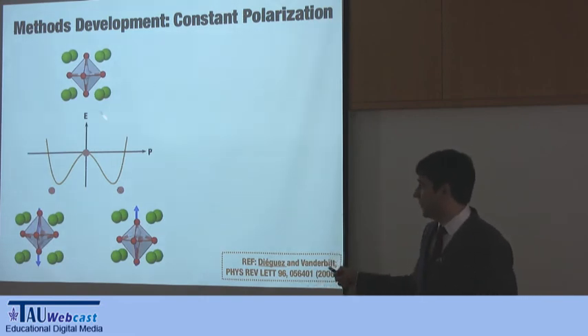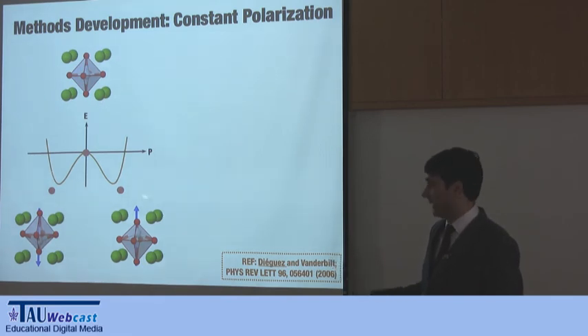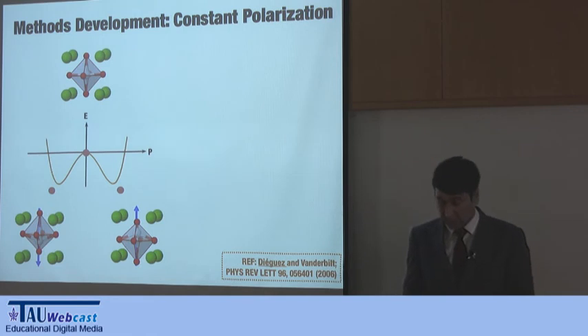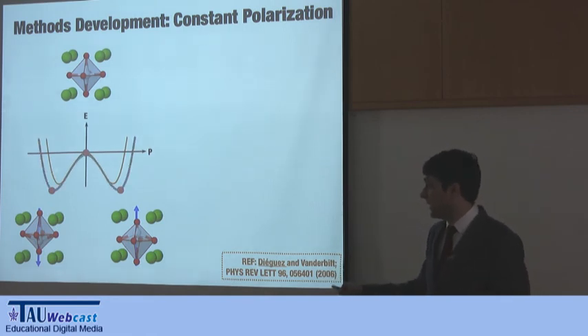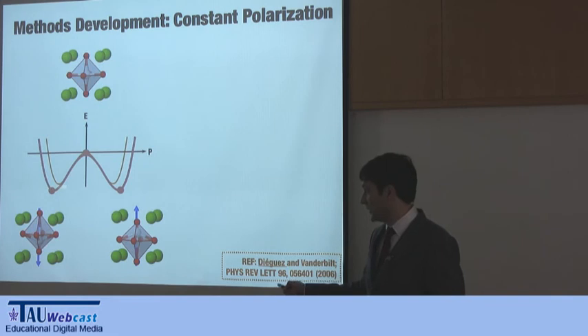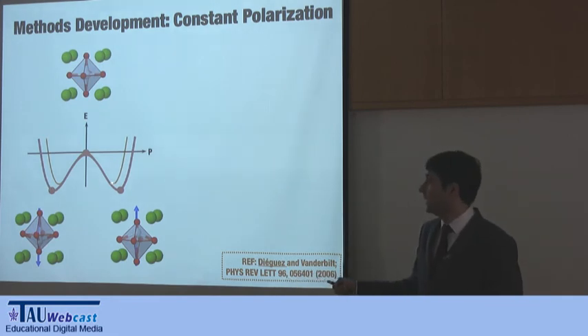So before, if you remember, I told you that there is a cubic phase at high temperature for barium titanate, that at low temperature goes to tetragonal phases, either up or down. And I told you that in these tetragonal phases, the displacements of the atoms are very similar to the ones of the soft mode here, but not identical. So one question that arises is, can you get a double well potential that goes exactly through there? So can you find, for a given polarization, what is the energy of the most stable configuration?